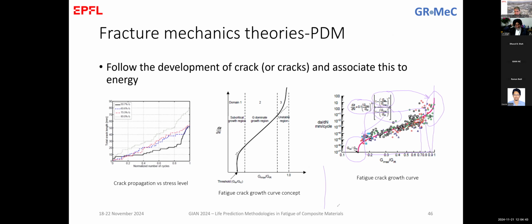You remember that also in the SN curves, we said that there is a value below which, more or less, we have very slow damage propagation. So in FCG curves, the fatigue crack growth curves, we also have a threshold below which, theoretically, we don't have any damage at all. This threshold is used by a lot of industrial domains to design structures for safe life. So design that does not accept any damage to occur in the structure. For example, aerospace designs airplanes with this consideration in mind. So they never accept having any damage in their materials. Of course, you can imagine this is a safe approach, but it is also very costly.